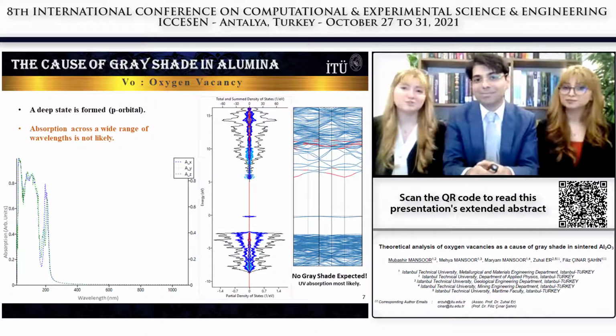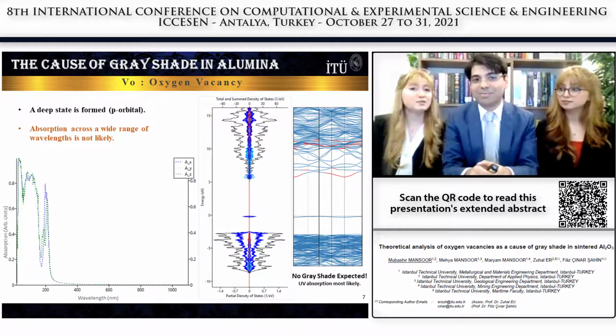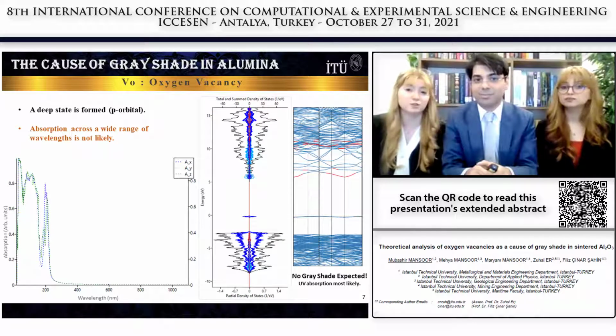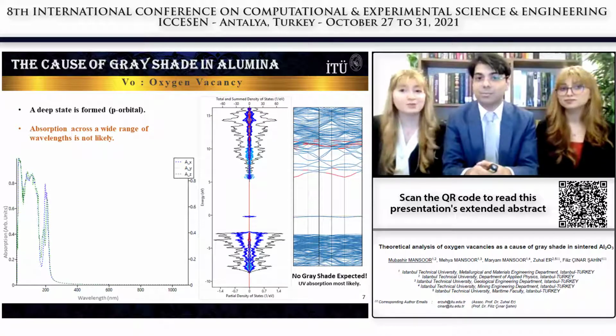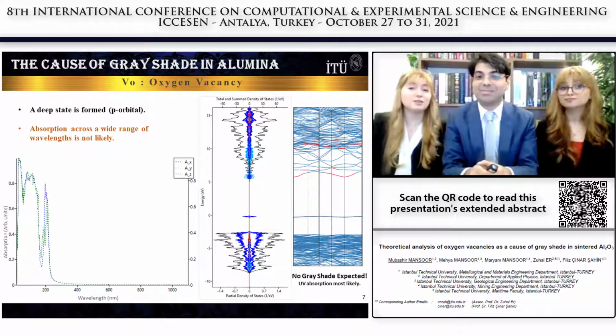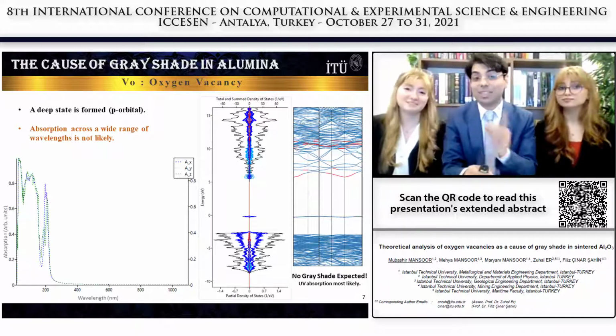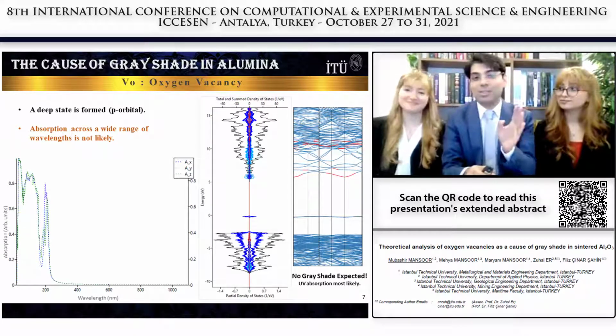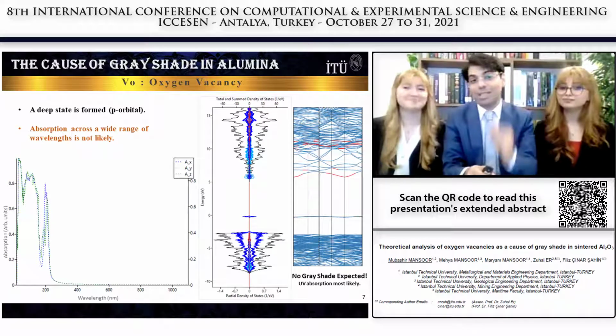Now, here are the results for the single oxygen vacancy. There is a p orbital induced deep band, which is seen here in the density of states and band structure plots. When we consider the absorption spectra, it is unlikely for this defect to have an absorption in the visible spectrum based on the MBJ LDA exchange functional. But one should expect absorption peaks in the short wave ultraviolet. It is also interesting that the energy of the defect level is almost independent of the K point. Now, this is very important because since the energy level is independent of the K points, it gives us the opportunity to do similar calculations in the future with much less computational cost.